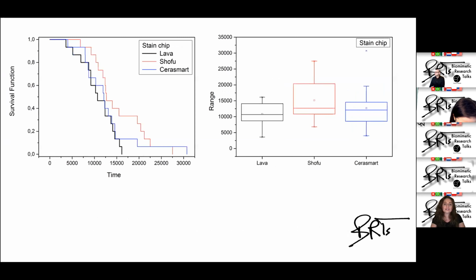What we've also checked is we've compared those between the blocks. There was also no significant difference here with regard to the initial failure. The final failure depended strongly on the type of the block and which material the block was made of. Here, the strongest one that we found was Cerasmart. However, all three of them, Lava, Shofu, and Cerasmart, always failed above strength and above the occlusal forces that we would expect physiologically in the mouth.